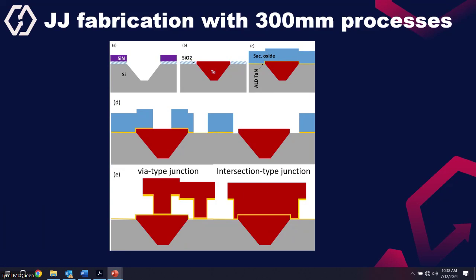So after creating this trench in silicon, we deposit the metal, which we are not showing here. After we deposit the metal, there will be hills and valleys, as Pop had mentioned before, and then we use chemical mechanical planarization. Here is the example of why we need chemical mechanical planarization: to remove the extra metal, and only the metal will remain in this trench.